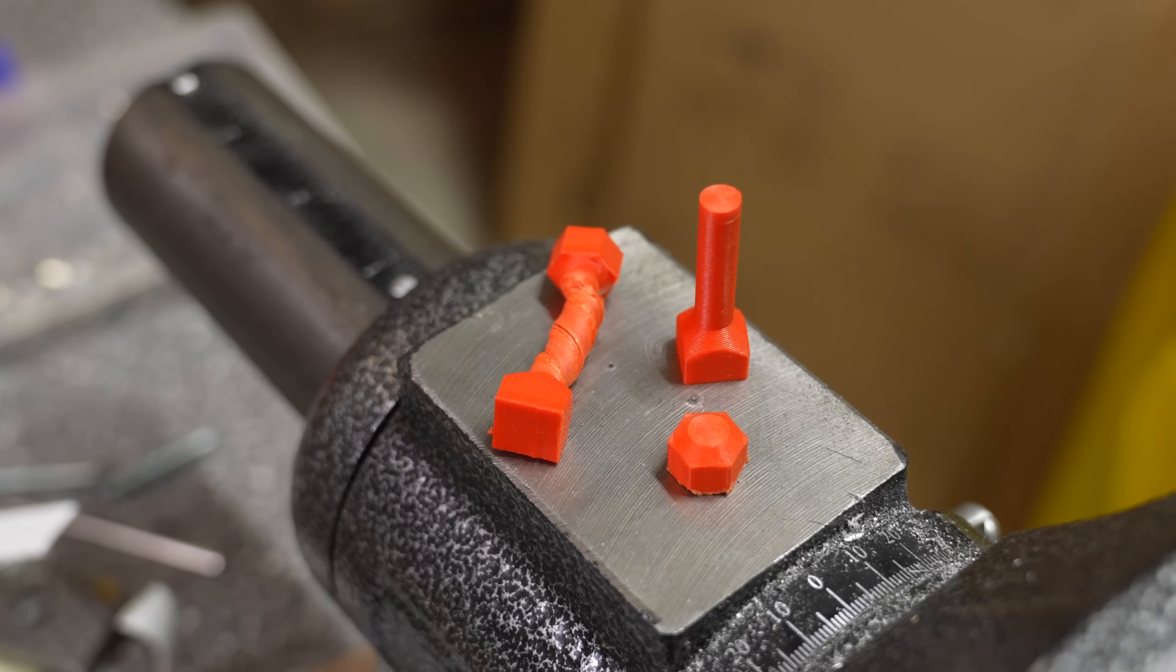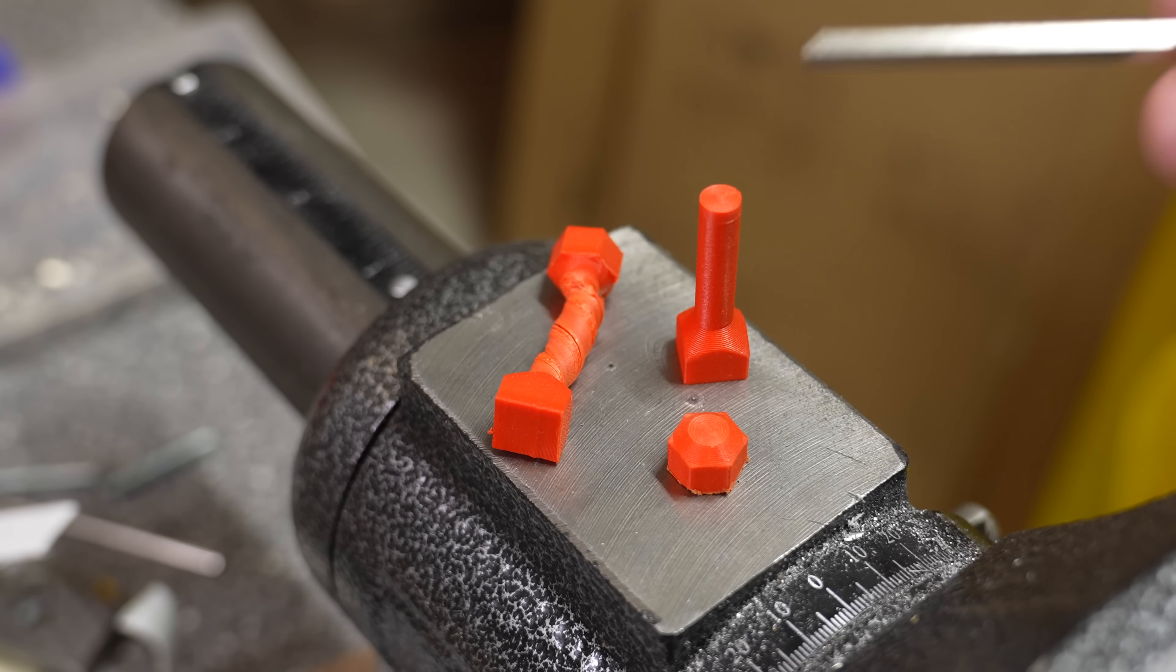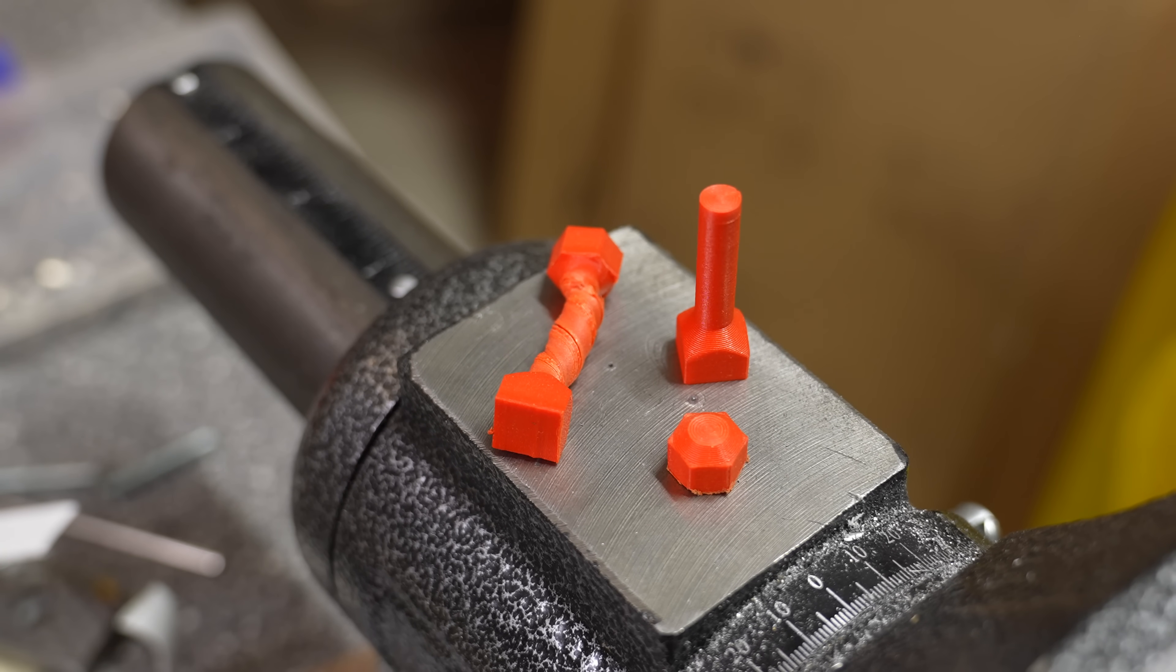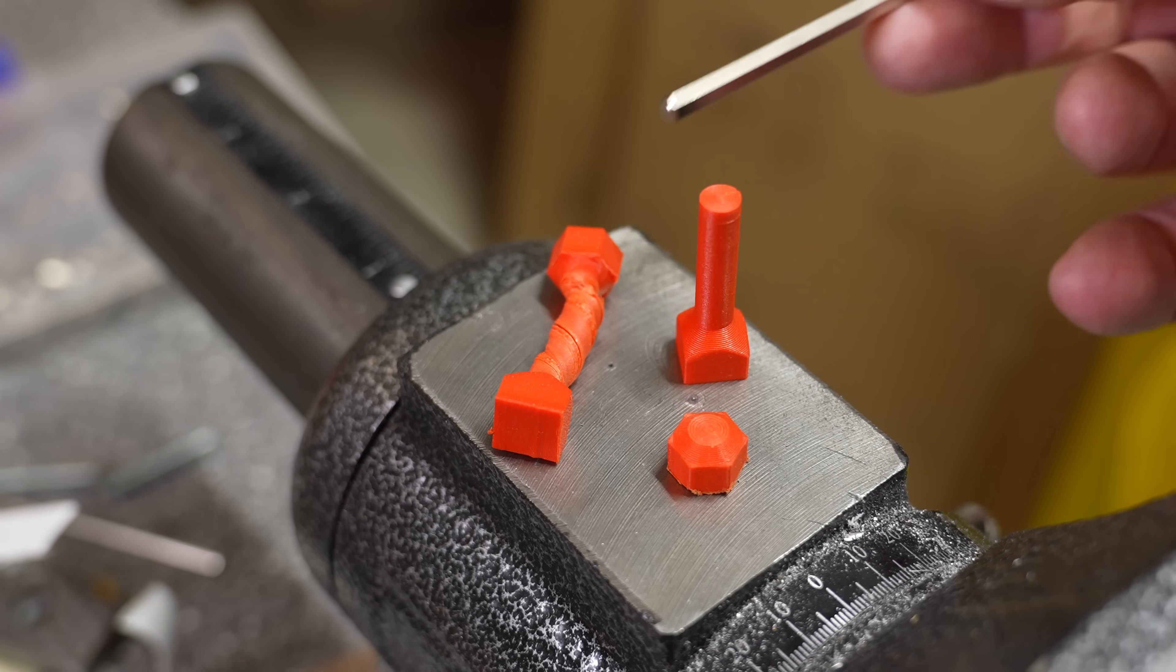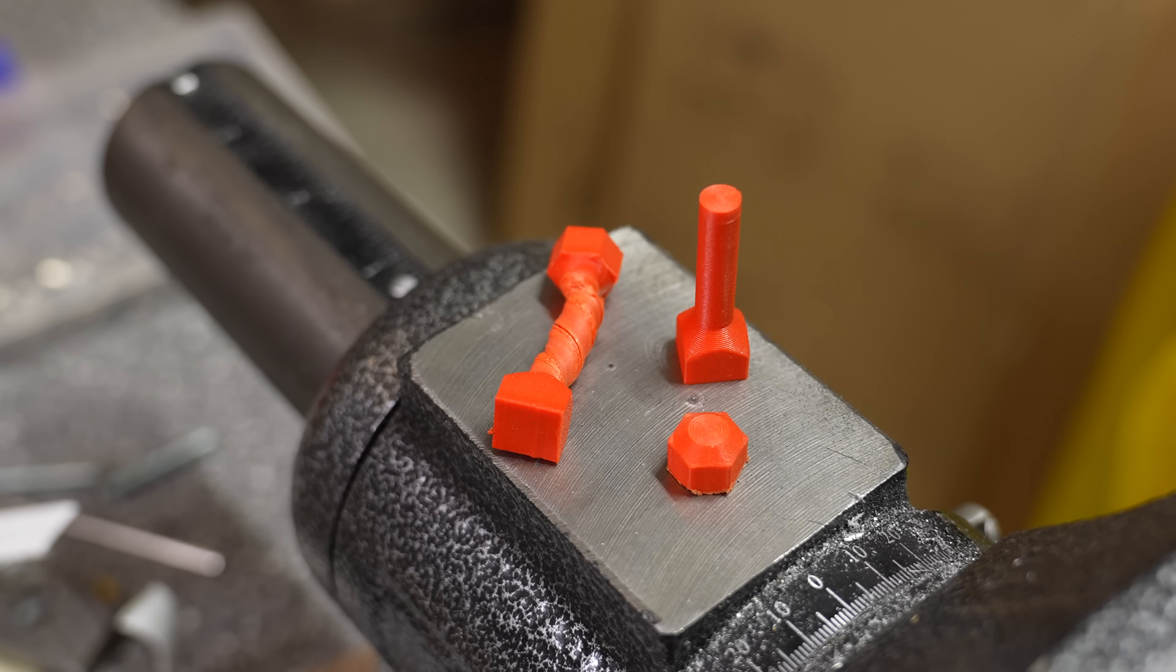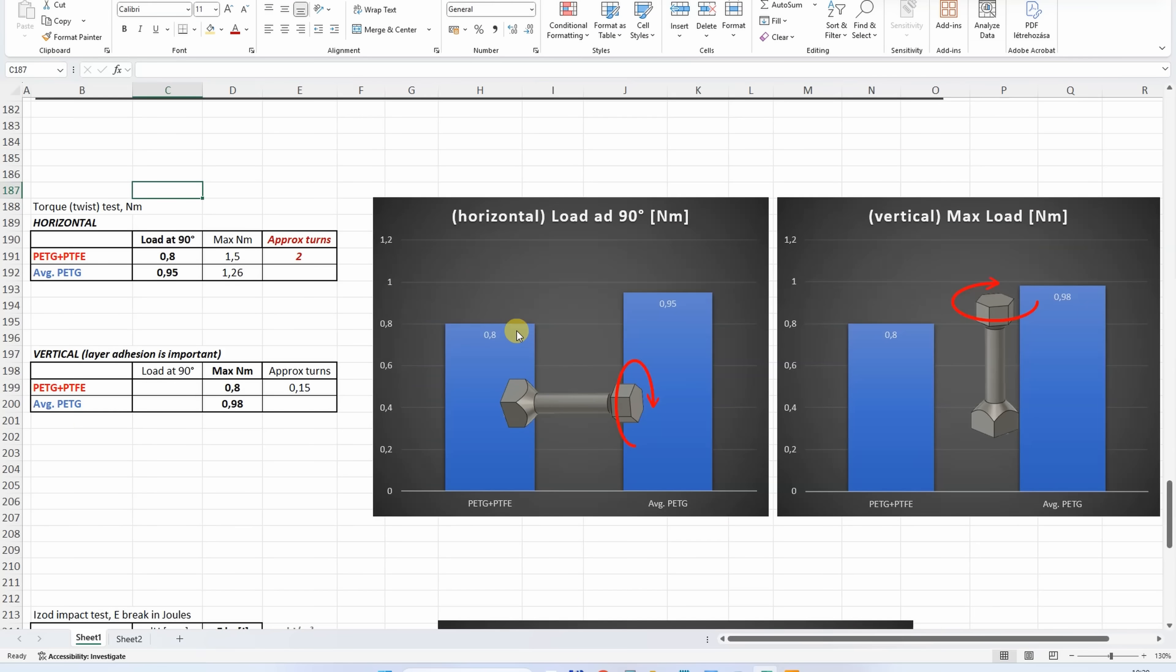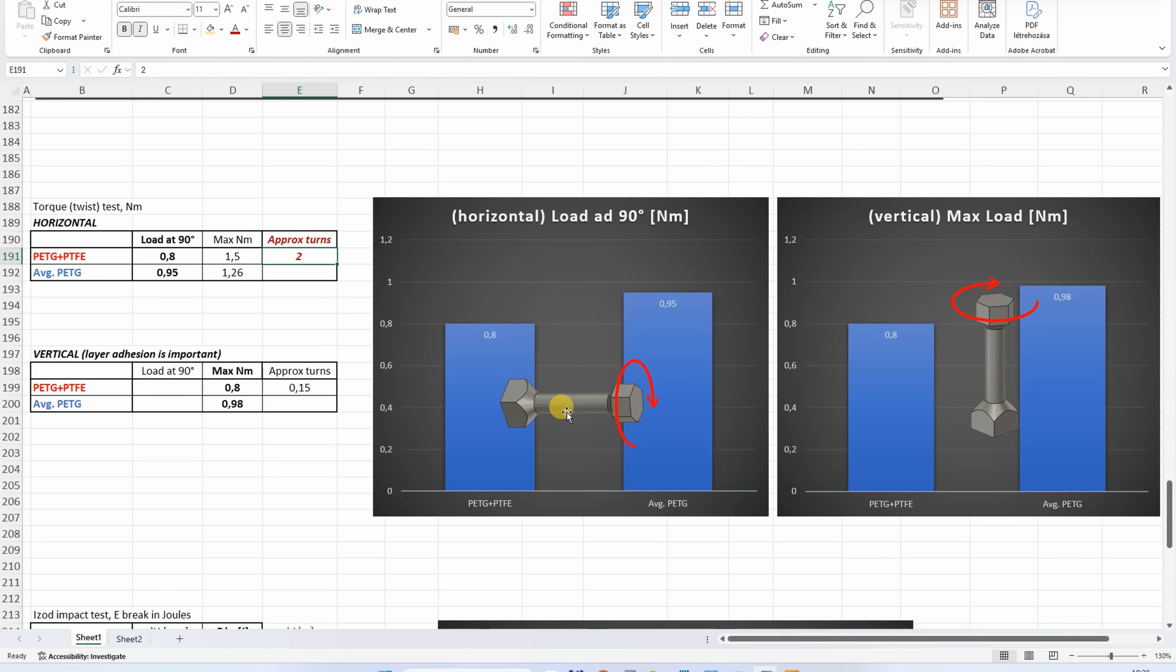I am not surprised that this printed in vertical position breaks very suddenly. But I don't really remember when I could make 2 rotations before the failure. Of course, for me, load and 90-degree rotation is more important. This Spectrum PETG was weaker by approximately 15%. But these 2 rotations before the failure was quite interesting. I am not sure if this is positive or negative. Decide yourself.